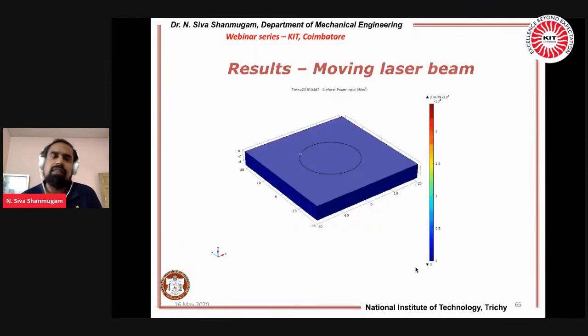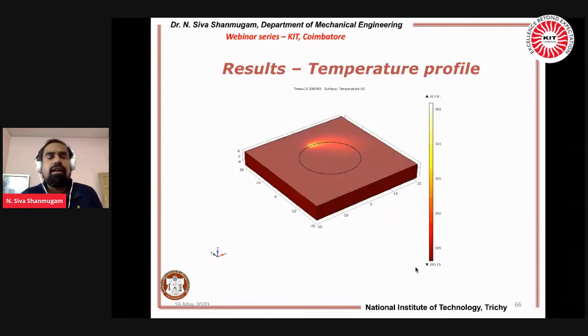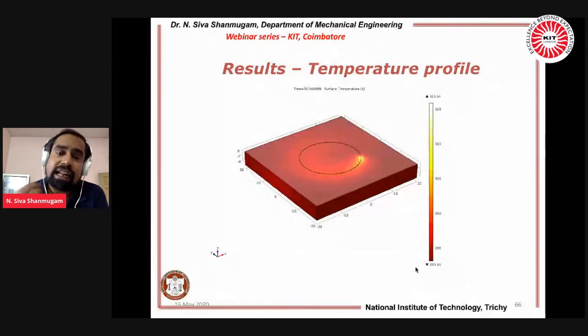And so far, I have discussed only the linear profile. When you go for the circular profile, with the cross wire you can fit the heat source at that point, and from that you can do the simulation. This is taken out from the COMSOL console. So we have an idea of how to work with this console. The capability of the console is that you can directly incorporate your own equation.